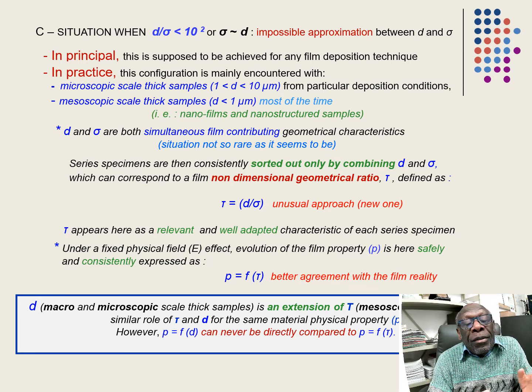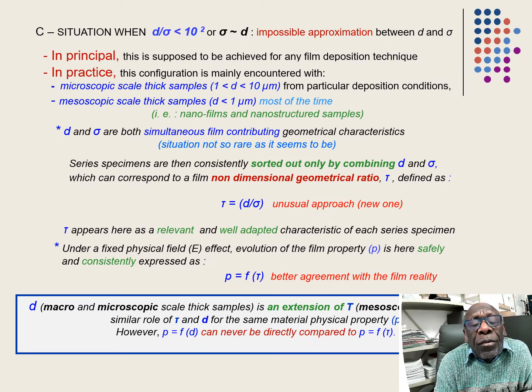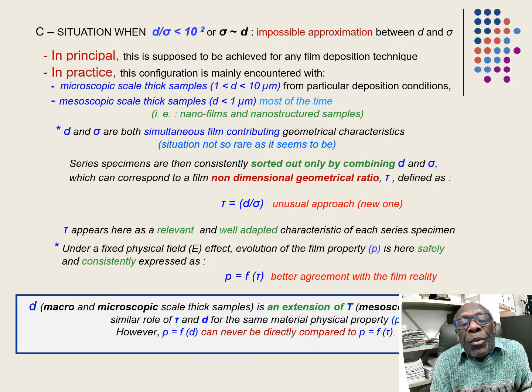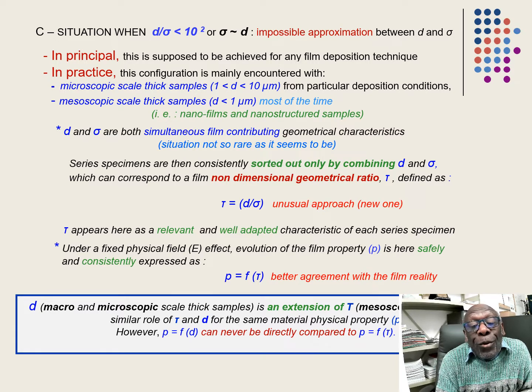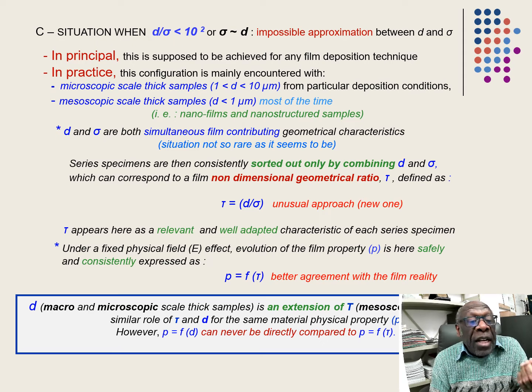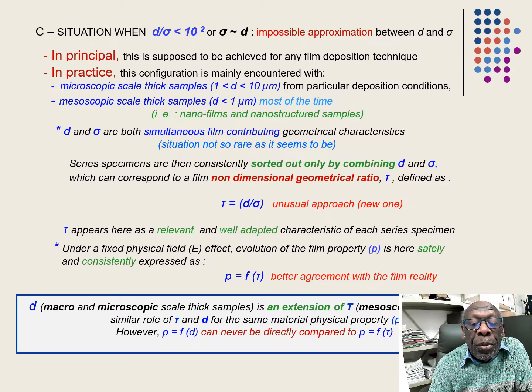In that case, I think that combining the two characteristics, that means maintaining the ratio and giving a particular identity to that ratio, as I'm presenting here, I give the identity tau. I gather the two characteristics through a third geometrical characteristic called tau. This is unusual. I didn't find that way of doing in the literature. But I think that tau is very relevant and adapted in that situation, so that you can study the evolution of your film properties using the expression P versus tau. This is in better agreement with the film reality.